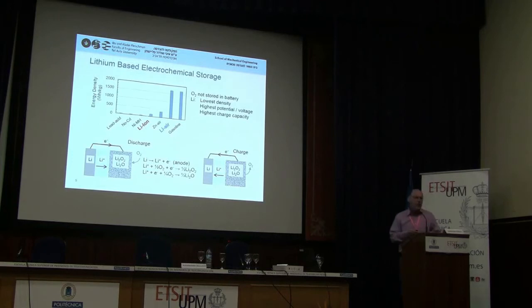But these materials were just the first choice. If we think about electrochemistry, the best material that is known is lithium. And I'm not talking about the lithium ion batteries, which are a commercial product. I'm talking about lithium air. So if we consider an electrochemical system similar to the zinc air that I mentioned before, but using pure lithium and the ability to take oxygen from the atmosphere and do the reaction and produce a lithium oxide, this actually has an energy density that is similar to conventional fuels, an order of magnitude higher than all the other batteries that are in existence today.